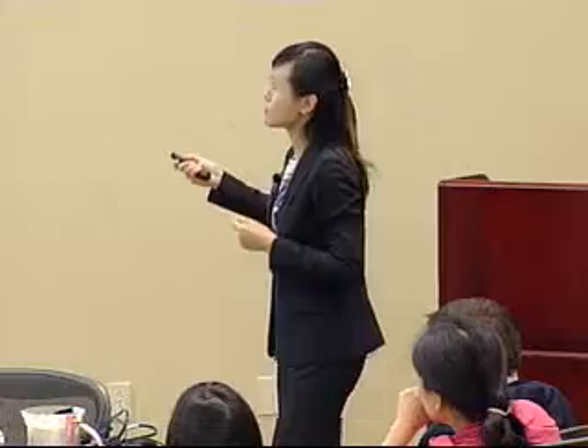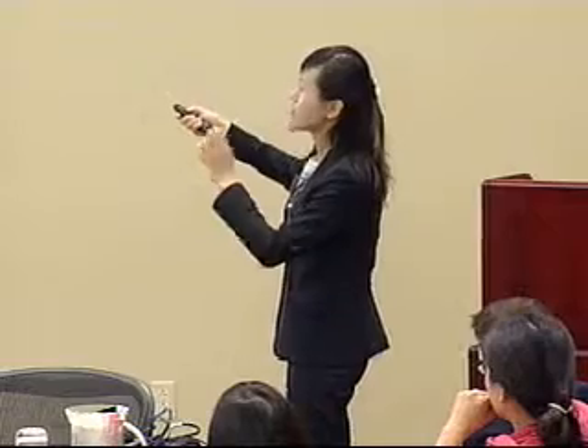But nowadays, because those pre-stretched substrates are not very microfabrication friendly, this becomes a more popular scenario where, instead of using continuous silicon membrane, we chop them up into isolated pixels of silicon islands. Those silicon islands are much, much stiffer than the substrate. And we can fabricate all sorts of inorganic transistors, diodes, sensors on top of rigid islands.